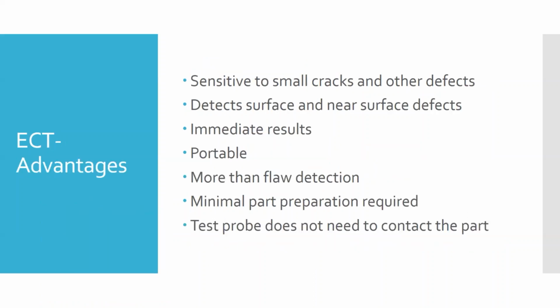So advantages of this are it's sensitive to very, very small cracks and other defects. This can find cracks that are almost too small to find with liquid penetrant, okay? And then it can detect the surface and near surface versus, liquid penetrant is probably the biggest competitor to eddy current testing, but liquid penetrant can't find anything subsurface. So if we're looking for not just surface but subsurface, this is a method we can use for that shallow subsurface down to that half an inch or so.